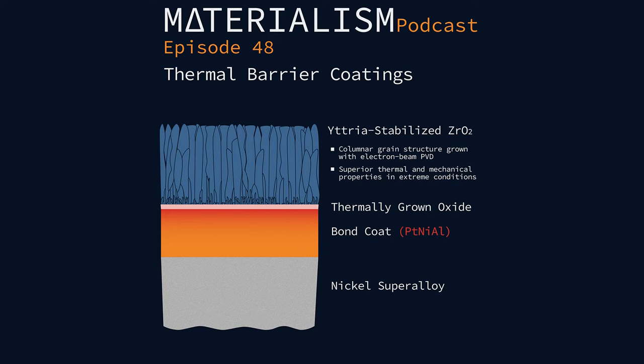All right, so if we start at the top of the superalloy, we move up into what's called the bond coat. Now, this is an alloy that attempts to do a number of things. The first is it aims to mediate the thermal expansion issues between the ceramic and the metal. By bridging this gap, it hopes to reduce the stresses that both of them are going to experience when the mismatch occurs. The other thing is that this alloy is composed of a number of different constituents, and when they are brought up to temperature, these constituents will evolve and in some cases decompose, but this is intentional.